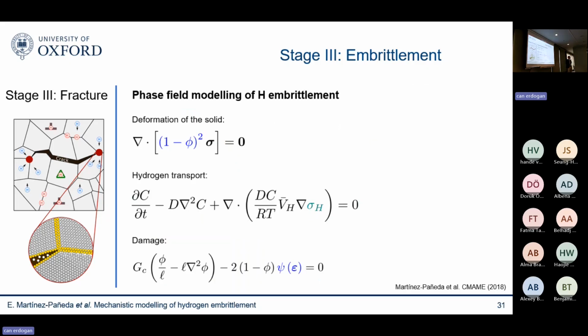And now we try to extend this to hydrogen embrittlement. We did this some years ago, and we thought, okay, if I try to develop the easiest phase field model for hydrogen embrittlement, then I have a three-field problem. I have the mechanical problem, I have the hydrogen transport problem, and then I have the damage problem. And you can see that they are coupled, and I'm highlighting here some of the couplings. But the most important coupling is, of course, how hydrogen degrades your fracture energy. How does hydrogen embrittle metals?